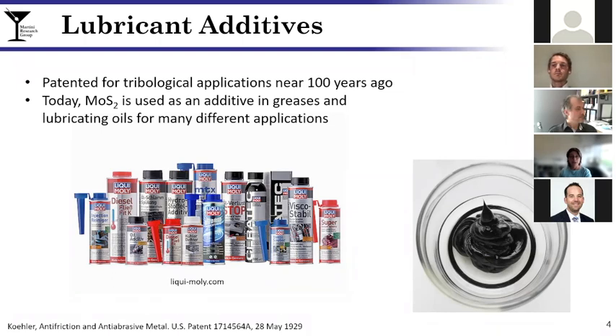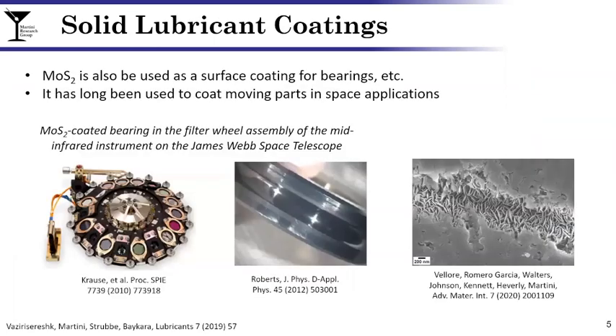The other application of MoS2 is as a coating or a solid lubricant or a dry film lubricant. The prototypical example here, as mentioned in the previous example, is space, where it's very cold such that one may not be able to use a liquid lubricant. Shown here on the left is an example from the James Webb Space Telescope, and in the middle is a bearing coated with MoS2 to be used without liquid lubricant. On the far right is an SEM close-up view of an MoS2 coating where you can see the lamellar structure evident in the crack that we're illustrating there.